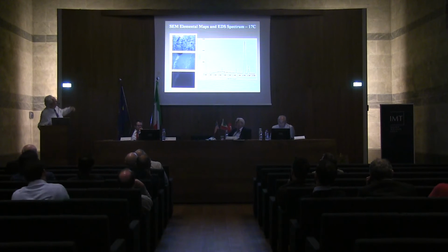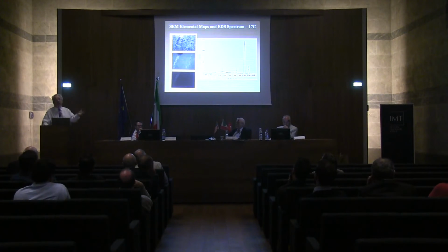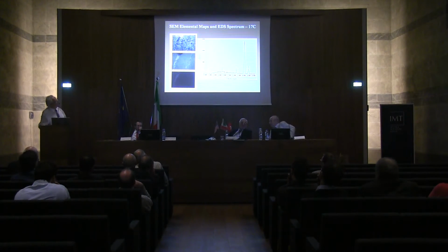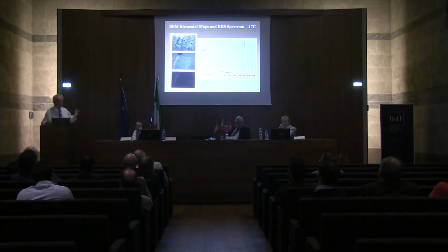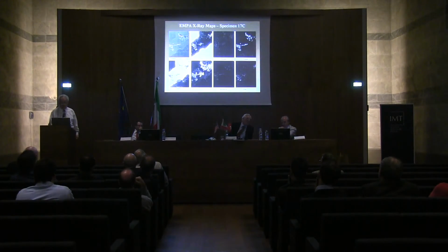You can see the top picture is a secondary electron image. The second one is a backscatter electron image, which is showing more the atomic contrast difference between copper and iron. And then the bottom is a copper X-ray map. And over on the right, you can see 2 big copper peaks, a small iron peak, a small tin peak, because it's a bronze, it's not pure copper.